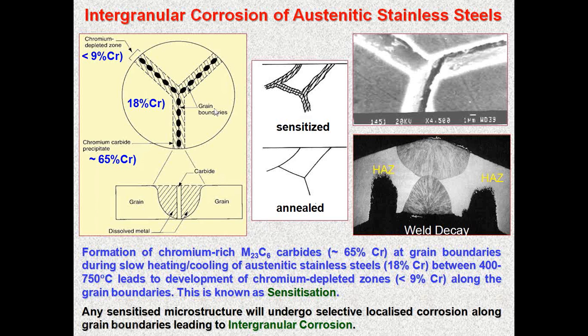What is sensitization? During heating and cooling, normally stainless steel, which contains 18% chromium, forms some chromides, chromium carbides along the grain boundary, which contain about 65% chromium. So the region which is very close to this grain boundary gets depleted in chromium, less than 9%. That means it takes away the passive film nature of the interface between the matrix and the carbide, which is very, very small in this line. So selective attack along this grain boundary takes place, that is leading to the intergranular corrosion.